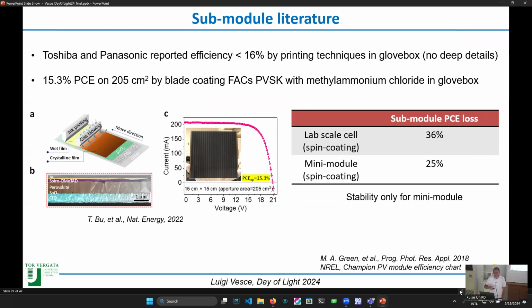There are plenty of examples about mini modules, but about sub modules it's really hard. For example, Toshiba and Panasonic showed something with efficiency about 16%, still in glove box, and it's hard to find deep details also because they are industry, so they do not want to publish all the details. There is this paper in Nature Energy with an efficiency of 15.3% on 200 centimeters square. It is still in the glove box, but they use some scalable techniques, like the slot die coating technique. In this case, you have a huge drop with respect to the lab scale cell: about 36% efficiency drop, and about 25% with respect to the mini module. So still a huge difference.